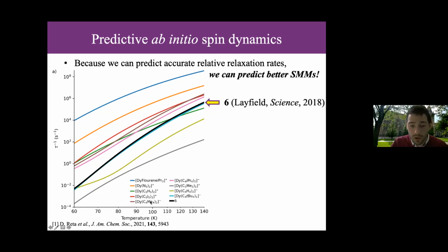And then we have a bunch of substituted and not substituted cyclopentadienyl and also cyclobutadienyl compounds. We did a bunch more, but this seemed sufficient to illustrate the point. Some are predicted to be worse than the black one here, which is compound 6, which is Layfield's Science paper. But noticeably, 2 of them are predicted to be far, far better, orders of magnitude better. And they are, perhaps unsurprisingly, the bare cyclobutadienyl anion, and I'll talk about that in a second, and then also the Cp star or C5 methyl 5 cyclopentadienyl molecule.